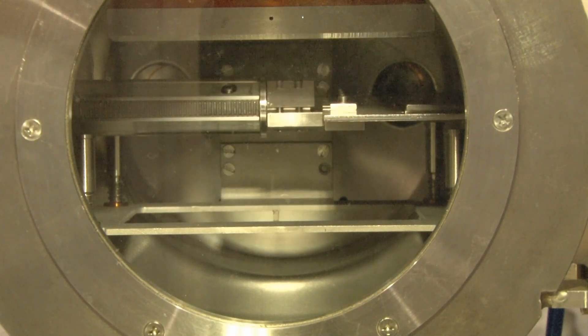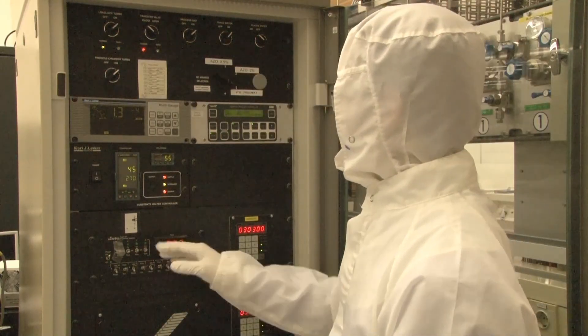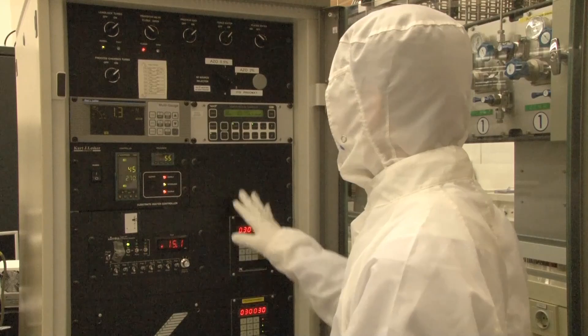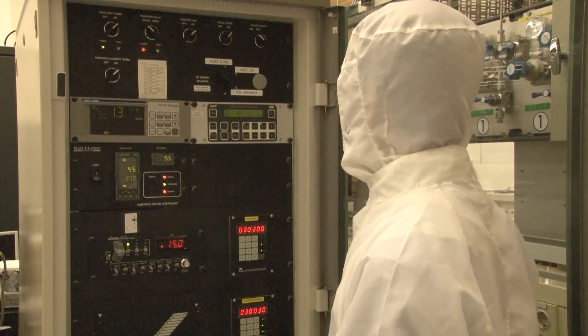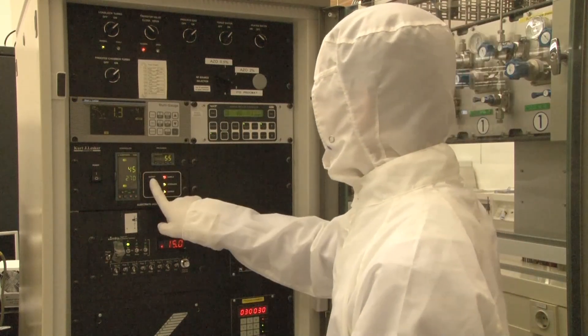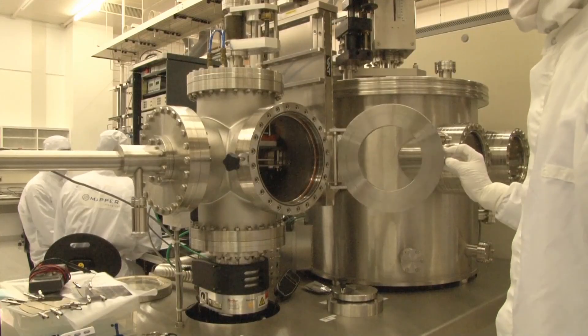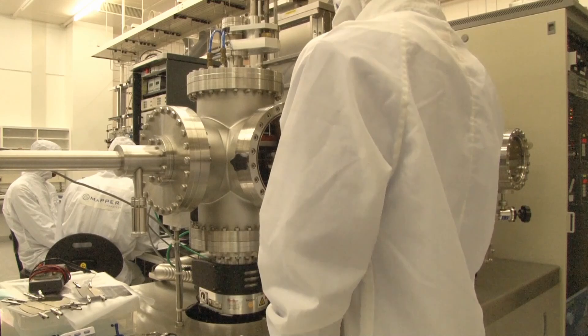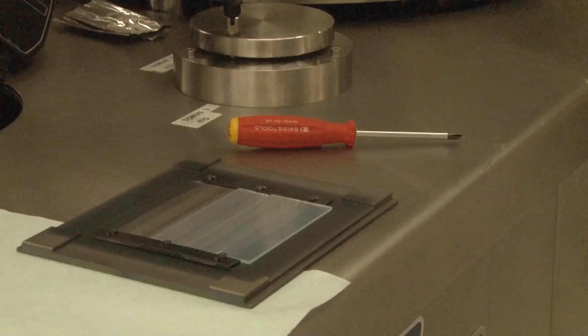This avoids the processing chamber from being contaminated with various unwelcome atoms and molecules present in ambient air. During sputtering, the zinc oxide target is bombarded using an ionized noble gas like argon. The generated aluminum zinc oxide species are sputtered into the chamber and deposited onto the substrate. Here you see the sputtering plasma. After the sputtering processing step, we have a glass plate with a tin oxide with on top a very thin zinc oxide layer.